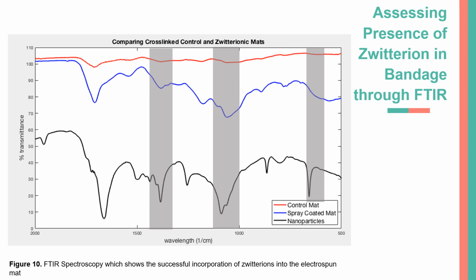For the analysis of our FTIR results for the Zwitterion in the bandage, we were able to determine the Zwitterion was in the bandage. As you can see from these highlighted peaks, the nanoparticles in solution create distinct peaks on the wavelength scale. Compared to the spray-coated mat in blue, these peaks are present, versus the red control mat did not have these peaks present.